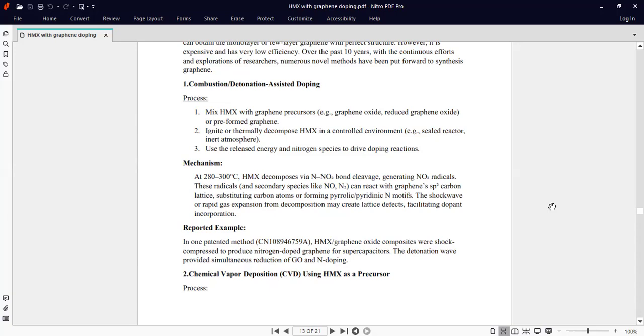Ignite or thermally decompose HMX in a controlled environment. The controlled environment can be a sealed reactor or inert atmosphere. Use the released energy and nitrogen species to drive the doping reaction. Now, the mechanism of combustion assisted doping is at 280 to 300 degrees Celsius.